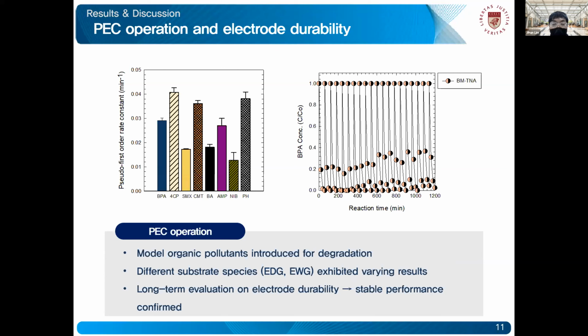To further confirm the feasibility and the performance of the novel BMTNA electrode, we applied the system to eight different organic pollutants commonly found in brackish water sources. Many of them include 4-CP, BPA, and phenol. Through the analysis, we found that different substrate species, for example the electron donating group or the electron withdrawing group, exhibited varying reaction rates. The phenolic compounds of the electron donating group more easily release protons into the solution under OH radical induced oxidation, and are thus more susceptible to photoelectrochemical degradation. In contrast, the benzene ring substitution of the electron withdrawing group hinders substrate degradation. However, long-term operation of the PEC system confirmed that all eight organic pollutants were successfully degraded.